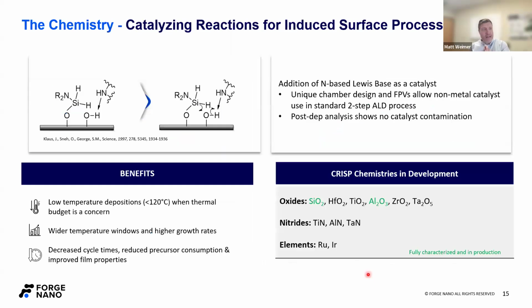All right, and finally, the surface chemistry that we like to take advantage of, we prefer to use surface catalysis over plasma. Again, as a chemist, from my perspective, when you introduce plasma or higher temperature, all you're doing is beating that poor reaction with a larger energetic hammer. If you want a reaction to go forward, there's other techniques that we have been studying for hundreds of years, such as catalysis. So using small non-metal catalysts to push reactions forward, really, you're lowering that energetic barrier to help them along, is a much more elegant way to do things.